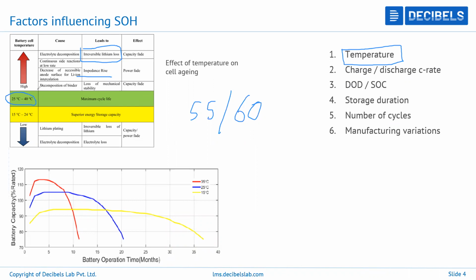Here you can also see certain electrochemical degradation starts to occur. That is the decomposition of the entire cell. Inside there are certain chemical binders, additives, and agents that basically keep the cell in one piece. But if you keep using it at very high temperatures, then this is what can happen.